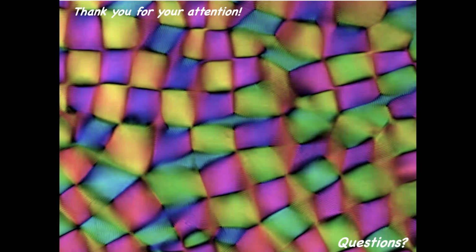Okay, thank you for this question. I'm not sure if I give you the right answer, but I will give you one answer. I'm trained as a polymer physicist, okay? And when we started to look into this system, I said, okay, the fibers have a persistence length of 2 microns. I break them down to 900 nanometers, 800 nanometers, they are extremely rigid, okay? We see nematic, we don't see cholesteric. And that's why I said, okay, that's way below the persistence length.